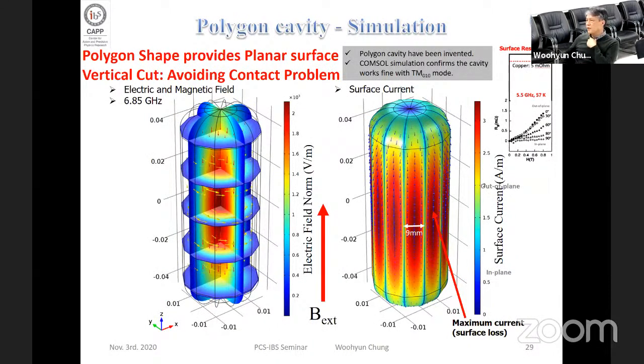Our solution was, to me, easy, because the main mode that we're using for the resonance is the TM010 eigenmode. In this simulation, you can see that all the electric field lines are aligned through the surface. What this tells you is that when you split the cavity vertically, it doesn't have any effect on your Q factor. So we actually use a vertically split cavity for our normal axion experiment, but here, because of the shape, we have to cut it into many more pieces.